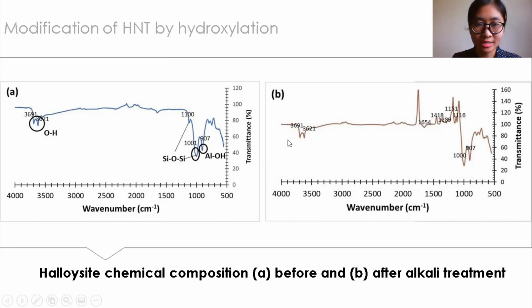After mild hydroxylation, the characteristic peaks for halloysite are still there, so we can say that the tubular structure was maintained. There were a few small absorbance peaks discovered here, near the siloxane peak, which may indicate a change in the bond stretch of silicon and oxygen molecules.